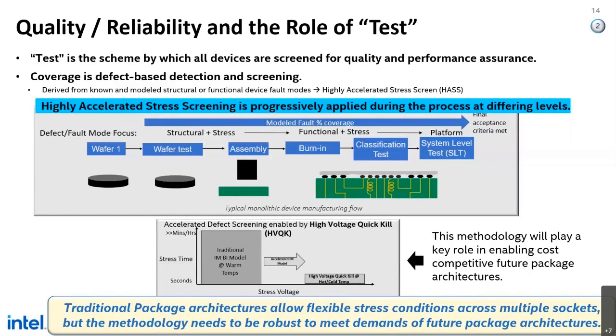And the way that we would do it from a new technology development point of view is we would start with wafer level sort or testing there. You can apply a stress at wafer level before parts go into assembly and start the screening there. And that could be a structural test, or it could be even a reliability test in line in the wafer process. And then you move into assembly and you're going to do some more testing and more burn-in. So you'll do another structural test, another burn-in, and you're going to find more failures. And those will be latent failures. After that, then we'll move into classification test. And then subsequent to that, you can validate all of this on a system level test.